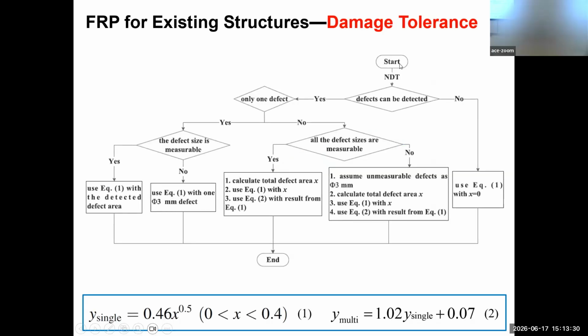Then we developed a design procedure for FRP strengthening of steel structures, considering the interface defect. In practice, after you install the material on site, you always do NDT testing to identify defects and check the quality of the bond. If you detect a defect, you need to ask yourself: is it a single defect or multiple defects? If multiple, you follow the flow line and use this model to work out the reduction factor.